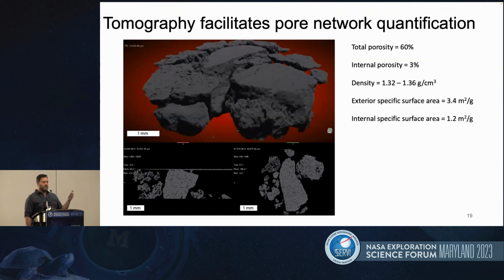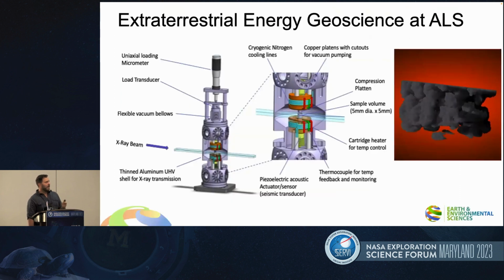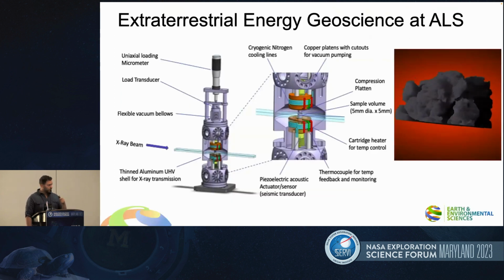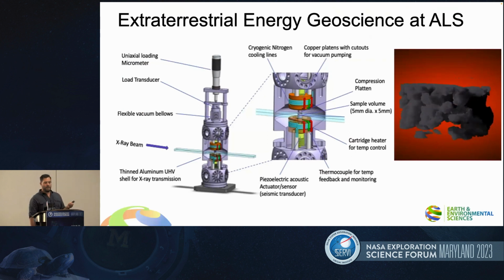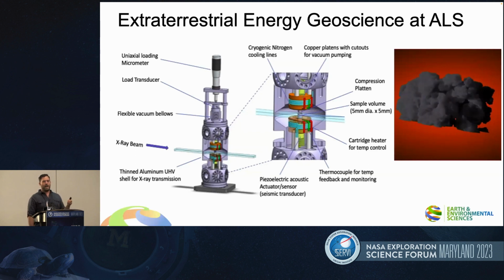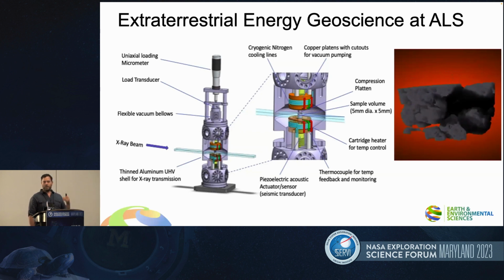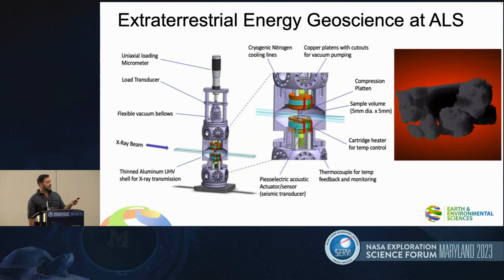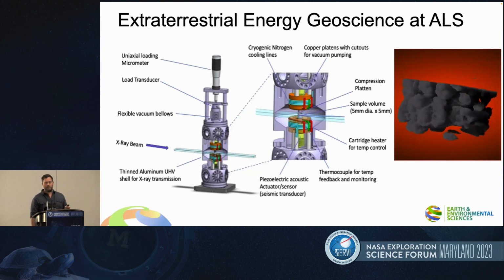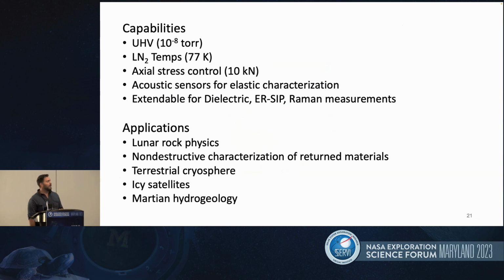We've done some initial quantification of this particular analog material, but there's a lot of work to be done. And more importantly, the title of this talk: we've been developing an X-ray transparent, ultra-high vacuum cryogenic vessel that will allow us to do imaging at real lunar surface conditions, so that we can make a real appendix with real geometrical data about the topology of different textures of ice within the regolith. The first version of this is going to have integrated acoustic sensors, so we can do the same kind of measurements that I was reporting from the benchtop. We'll be able to get down to ultra high vacuum and liquid nitrogen temperatures.